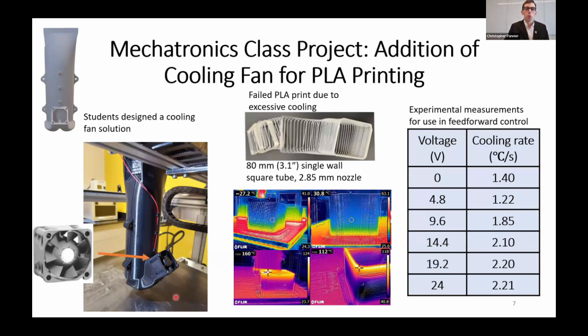So the students hooked this up. Then they turned the fan on full speed and printed a part and ended up making a slinky. So this square tube that was made was printed with excessive cooling. In that case, the layers didn't adhere together because the under layer was too close to the ambient temperature. So that's a cool thing. We didn't think you could make a slinky by extruding with a 2.85 nozzle. We didn't think about that option, but that's a cool application we came up with.